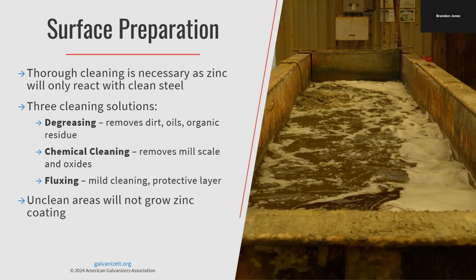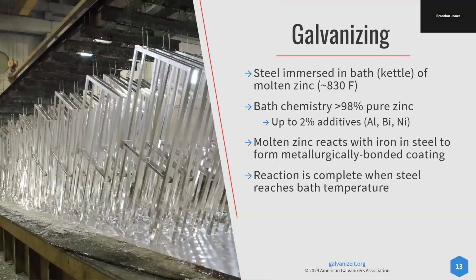And then fluxing is actually two things. Mild cleaning gets off anything that is left on there, and it also puts on a protective layer. So while that piece is waiting to go into the zinc bath, it's not picking up anything, because once again, unclean areas will not grow that zinc coating.